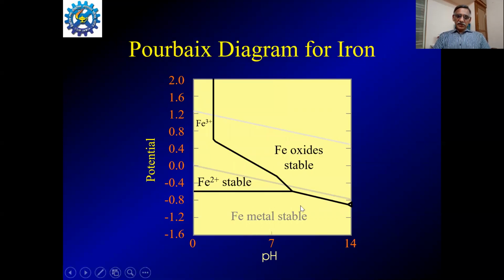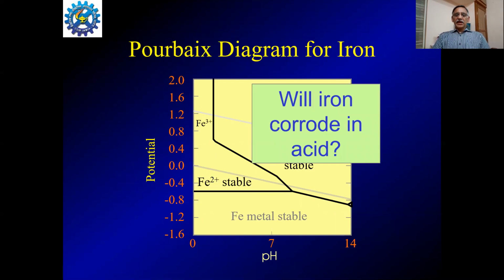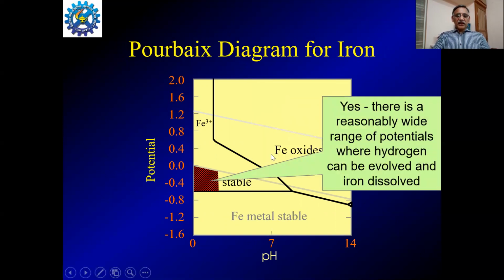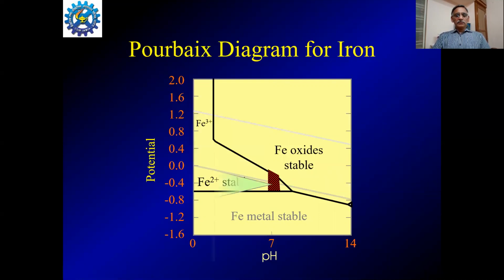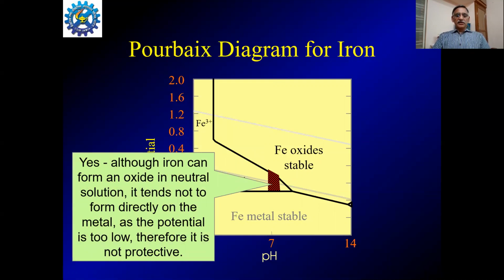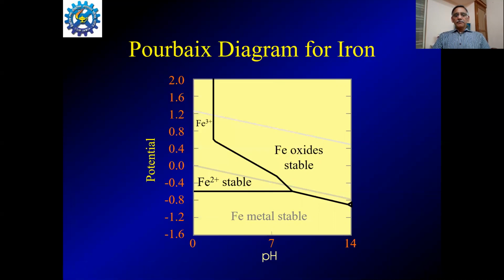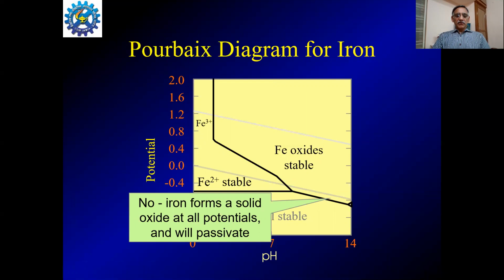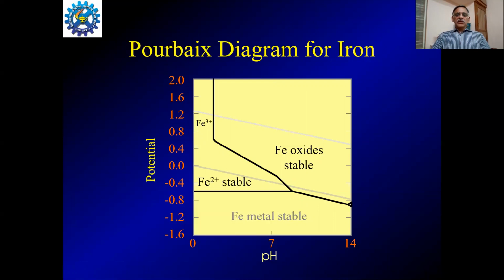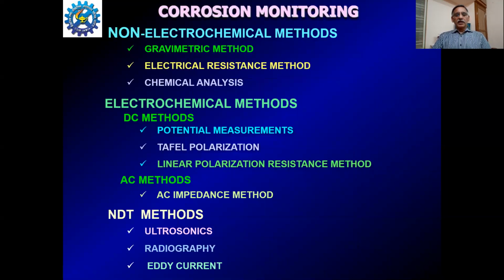Similarly, for iron, we have this immune domain. This is the corrosion domain, and this is a big passive domain. Will iron corrode in acid? Yes. Here we have the corrosion domain, and the hydrogen line is also there. So by hydrogen evolution, it normally corrodes. Will it corrode in neutral? Yes. In neutral also, by oxygen reduction, it will corrode. In alkaline, no. Iron forms a solid oxide over the surface and hence it gets passivated. So this potential-pH diagram is a very good tool to examine the various domains, whether the metal will get protected, is totally free of corrosion, or undergoes corrosion.